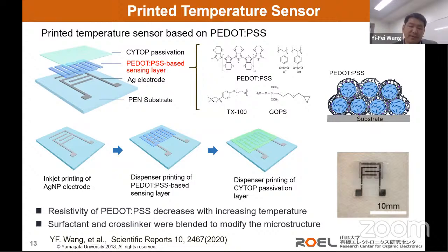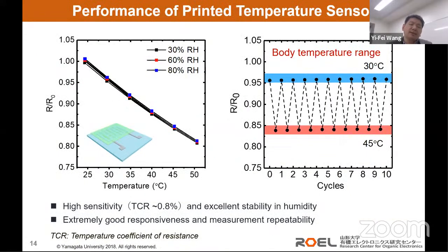And after developing the ink, we fabricated a fully printed flexible temperature sensor. The electrode was made by inkjet printing, and the sensing layer was printed by dispenser, and then a fluorine-based polymer was used as a passivation layer, also realized by dispenser printing. And then here I show the performance of our developed flexible sensor. When the humidity changed from 30 to 80, there is almost no change in the response of our sensor. So it shows a very stable temperature sensing performance. That means we realized a humidity-stable temperature sensor.